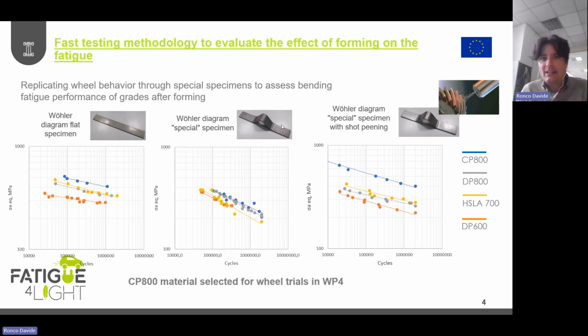And at the end, we investigated some special mechanical treatments on the specimen. For example, we investigated shot peening and laser peening, and in this graph we have the results with the shot peening. As is visible, the performance for the CP800 shot peened is really better compared to the DP600 shot peened. After this test, we selected the CP800 material